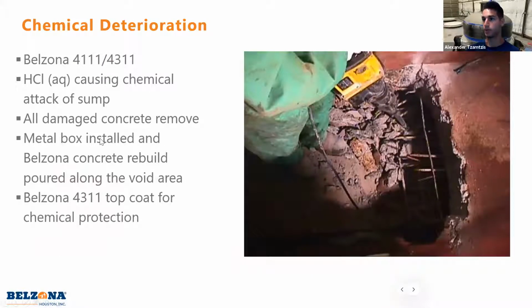So going into some cool applications here, we have a sump here that's concrete, as you see here, that was chemically attacked by HCl. So the way you apply these products, whenever we're applying them to concrete, the first thing you want to do is just remove all the damaged concrete. Yes, we have a great bond to concrete, but if your concrete is not intact, then that's going to chip off. So that's a big mistake that you can make, is just put it over loose concrete, because obviously that's just going to come off.